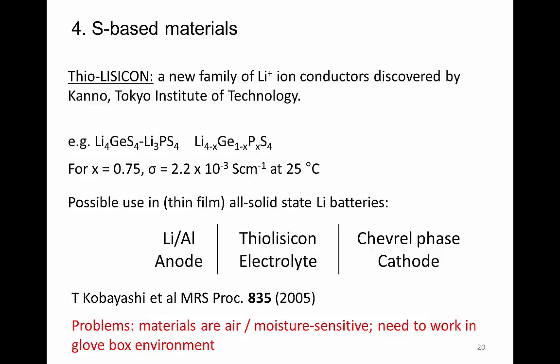LISICON is lithium superionic conductor. That's where the name came from. And so these are materials such as lithium germanium sulfide, lithium phosphorus sulfide systems, and here we have some conductivity data. So a typical conductivity, 2 times 10 to the minus 3 reciprocal ohm centimeters at room temperature. That's a pretty high conductivity.